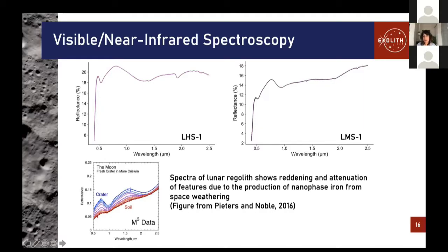So this is a good point to mention that our simulant is not space weathered. The primary driver of these spectral changes from space weathering is the production of nanophase iron, which happens over very long periods of time from the bombardment of energetic particles onto the lunar surface. And that is something you can do in a lab, but it's hard and expensive, and you can't do it with a large quantity of material.